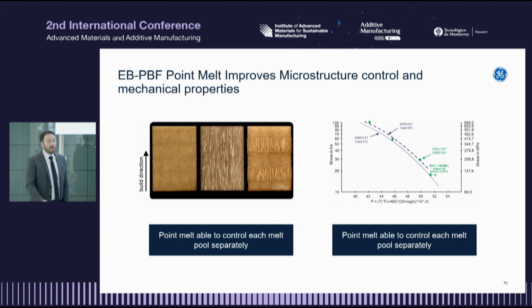One of the reasons we might want to proceed down a point melt path is tailored microstructure. What you're seeing on the left-hand side is a nickel superalloy called MAR-M-247, and the left microstructure is equiaxed. It's kind of hard to tell with the resolution of the picture and the PowerPoint here, but you have equiaxed structure. In the middle, what amounts to directionally solidified structure.